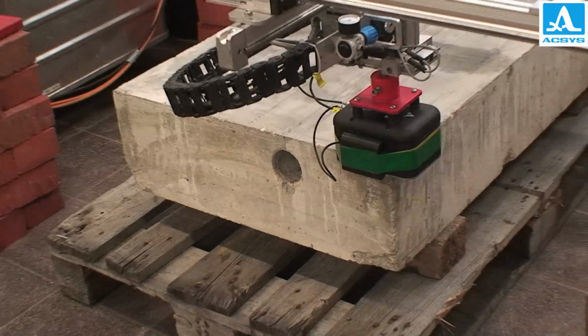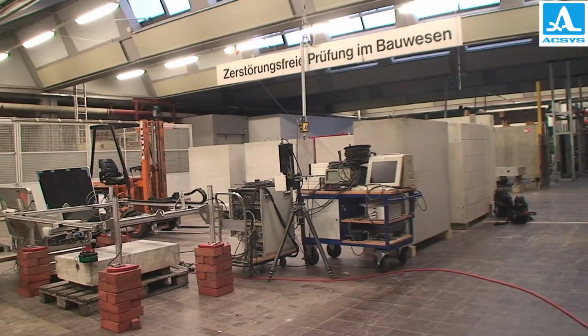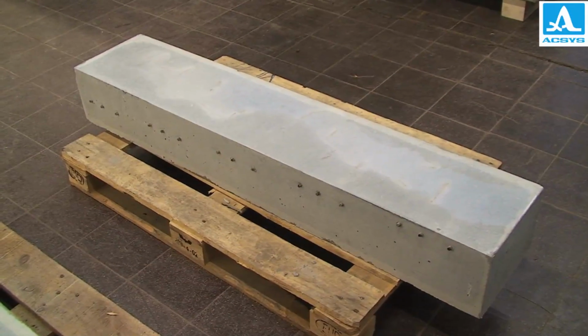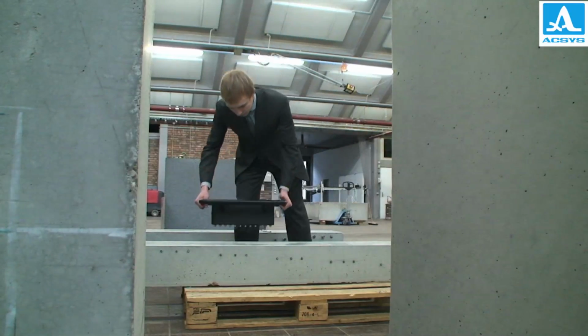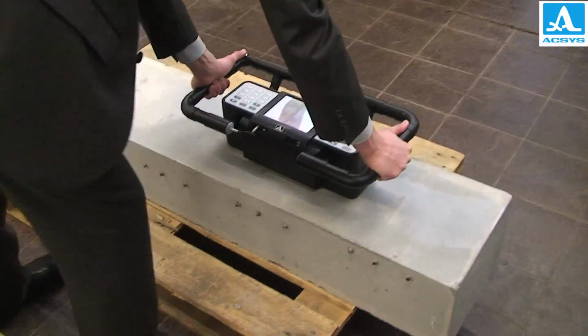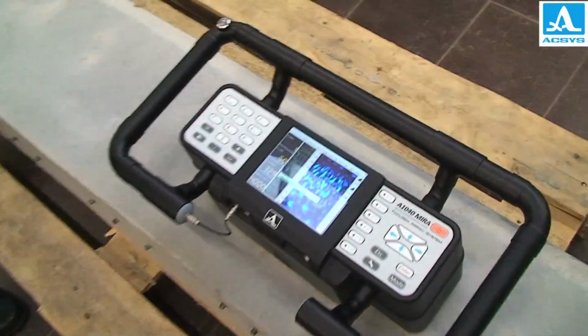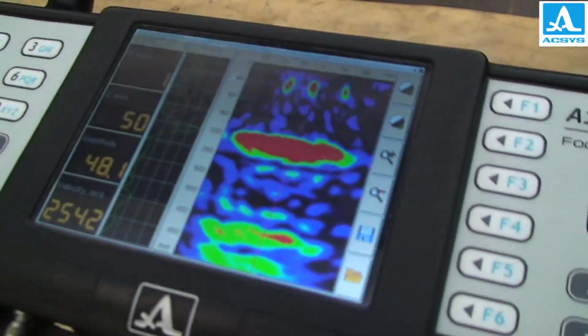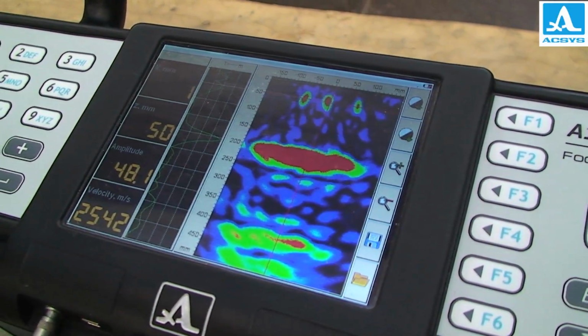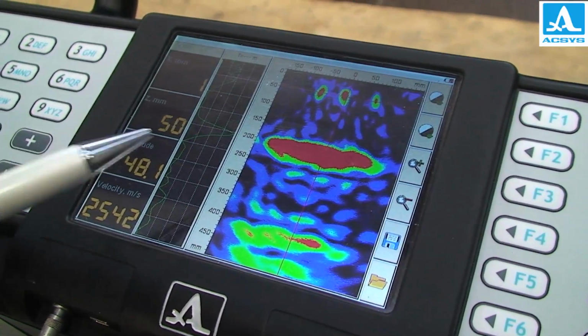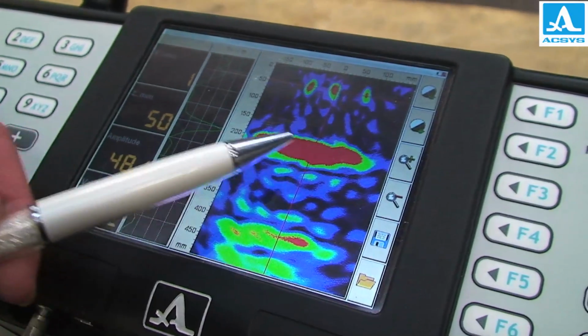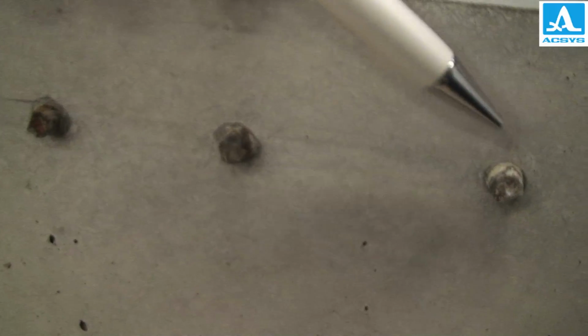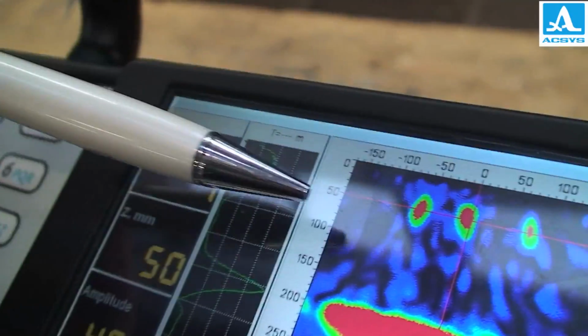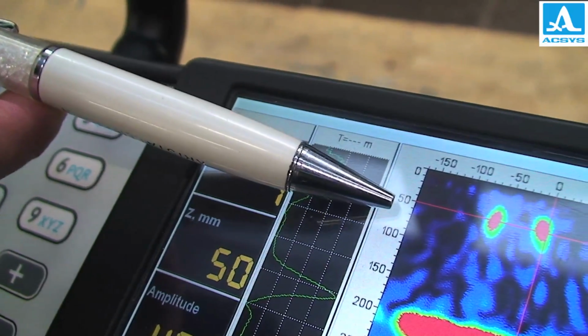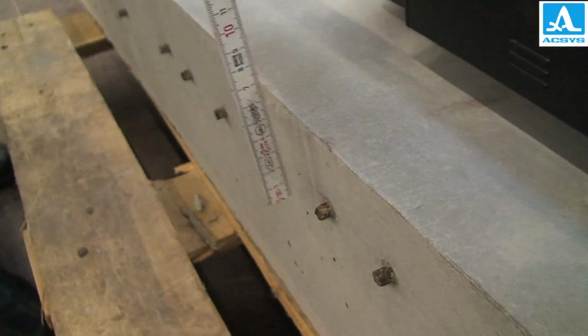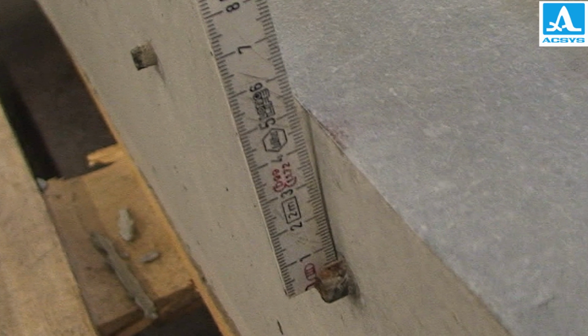The third sample tested was a reinforced concrete slab with reinforcing bars placed at various depths. The results of the MIRA testing show the location of the first set of bars at about 50 millimeters. In this tomogram, the bright red area at about the 200 millimeter mark corresponds to a reflection from the bottom surface of the slab. Above this reflection, three additional red spots are shown. These spots are reflections from bars located directly under the antenna array. The metric scale on the left side of the tomogram shows the location of the reinforcing bars at a depth of 50 millimeters from the surface.